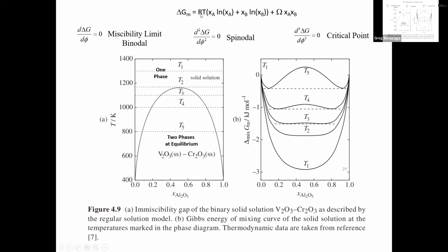If you vary the T, because the log of something smaller than 1 is negative, this term is negative. This is a change in free energy on mixing, so that drops the free energy. That's a good thing. So entropy drives mixing. Then this other term is generally positive. If you want to see phase separation, you have positive here. So they balance off each other, and you can get negative and positive free energy change on mixing. So if you plot that equation and vary the temperature, this is 1/T, and you get this kind of behavior.